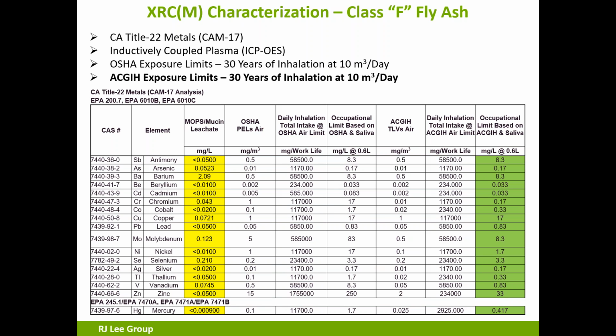In this case, we've now moved up to the California Title 22 metals, the CAM17, because it's a little more comprehensive, plus it's the most stringent that we can find in the industry right now. Again, ICP, OSHA exposure limits, or ACGIH. We decided to use ACGIH because they are the most restrictive levels for occupational exposures to these metals. And for those metals that actually have an occupational exposure limit, which all of these do, we found that this Class F cleared every one of those limits against the ACGIH.